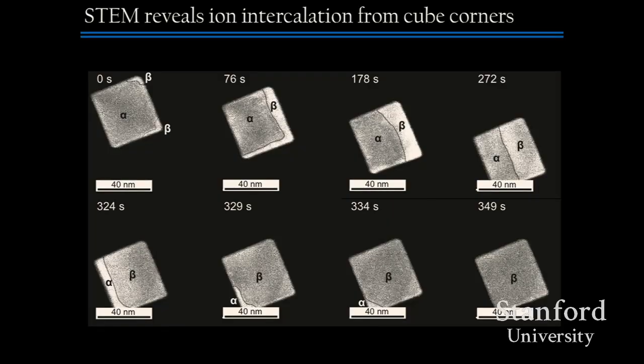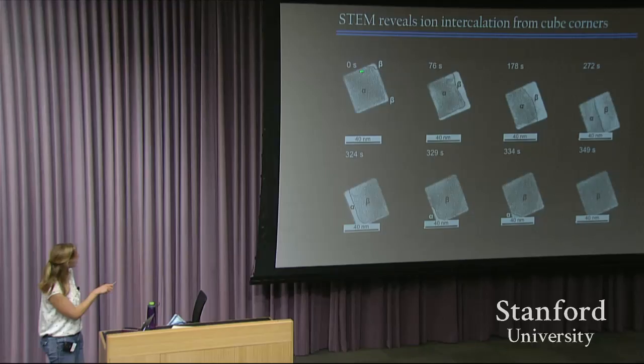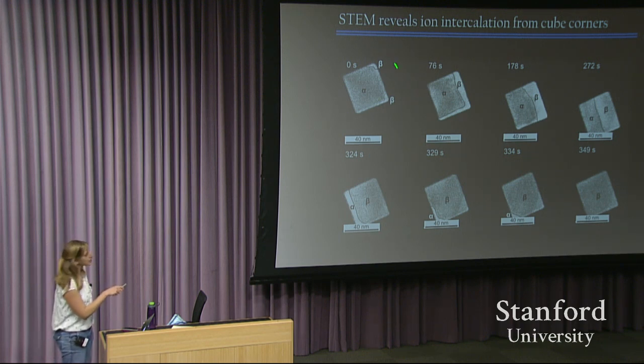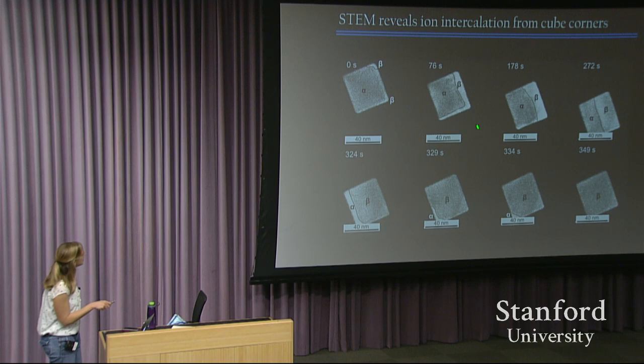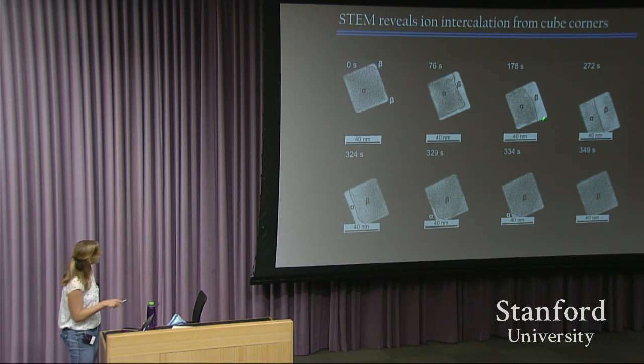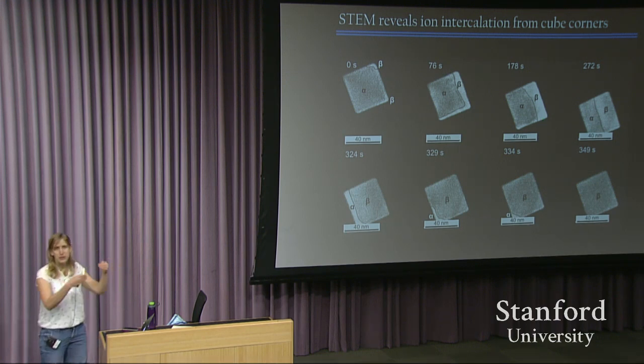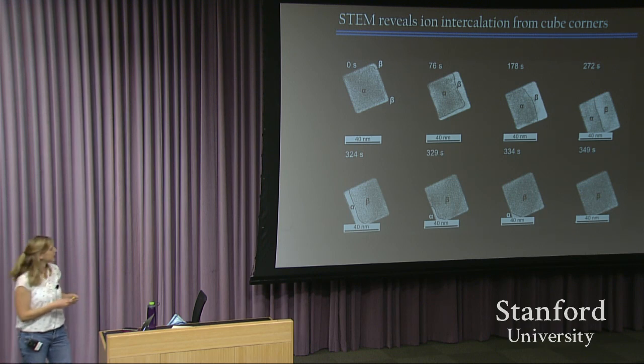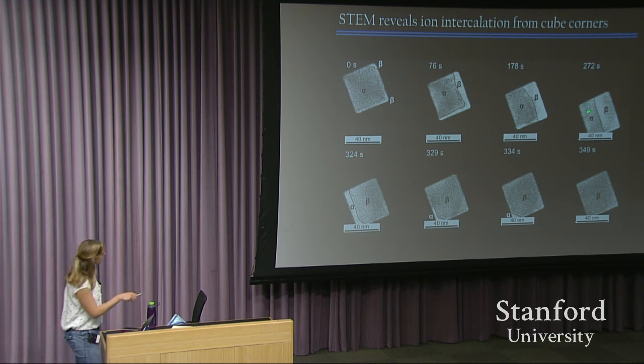So here are snapshots of that video where right when the video starts or shortly thereafter, the beta phase, the new phase, kind of grows in from the corner. You can see it's also kind of wetting the surface of the nanocube. And then eventually this beta phase aligns itself along a 100 axis of this nanocube. It marches across the nanoparticle, moving from 272 seconds to 324 seconds.